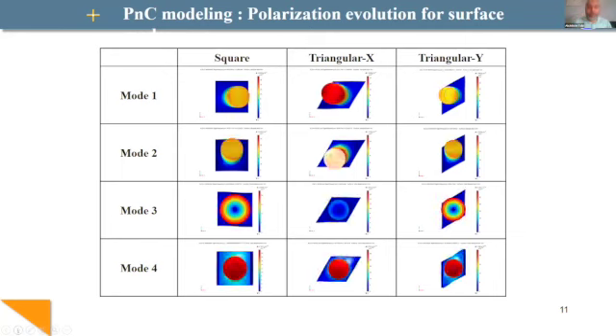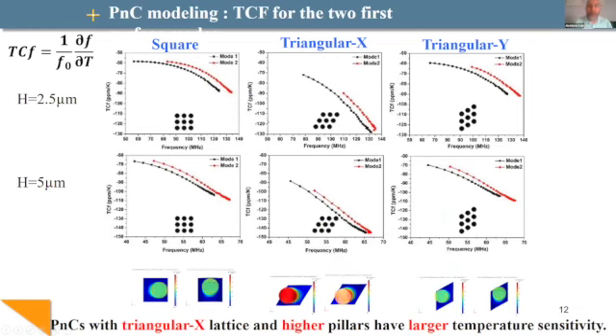Just from this analysis, we can see if there is some effect on the sensitivity to any physical parameters. In our case, we choose the temperature. The model is changed: we introduce the stiffness parameters and density as a function of temperature, and we calculate the eigenvalue as a function of temperature. And here we plot the temperature coefficient of frequency versus frequency. It means that for each mode at different frequency,